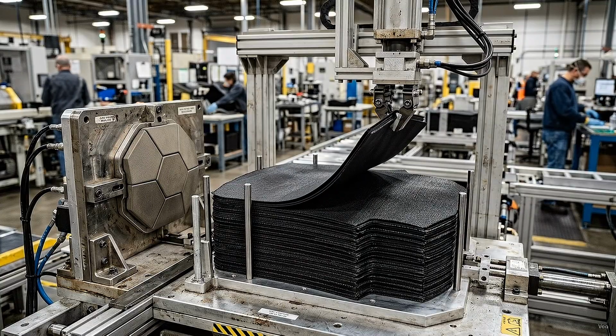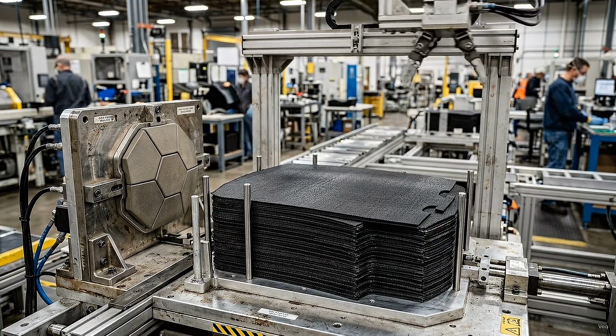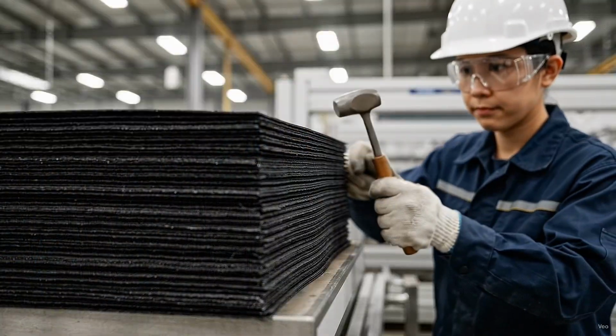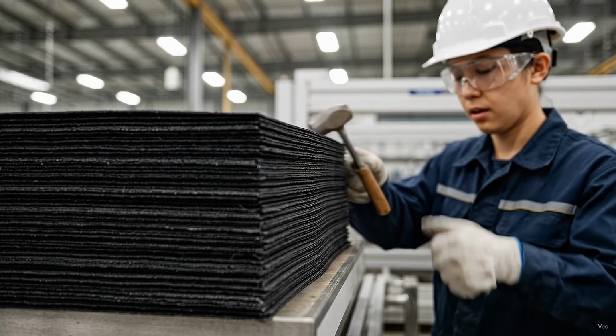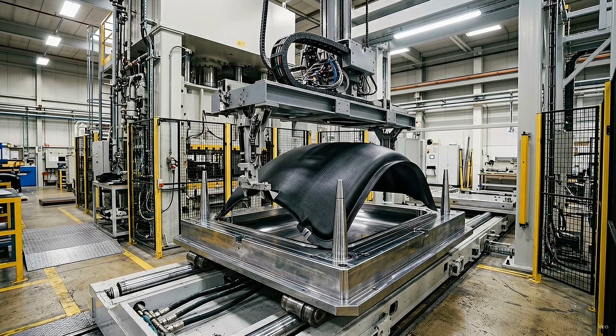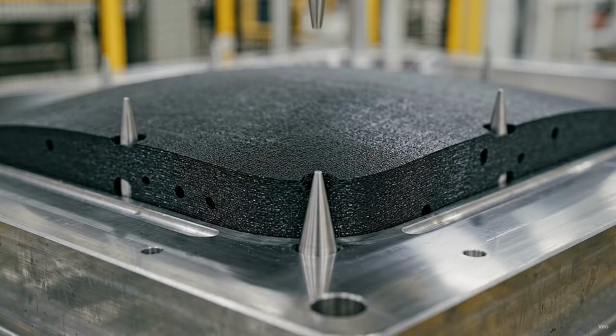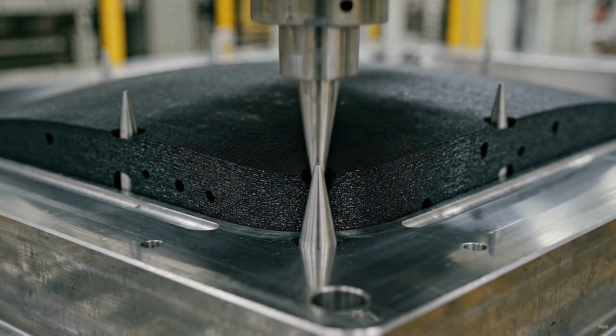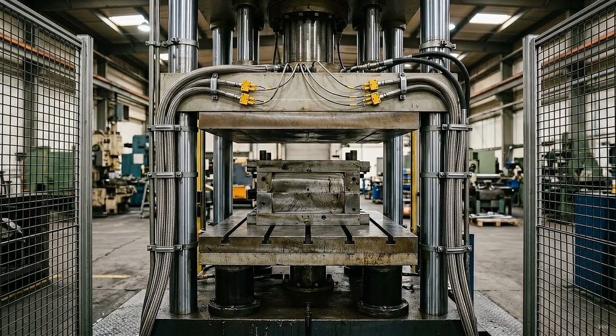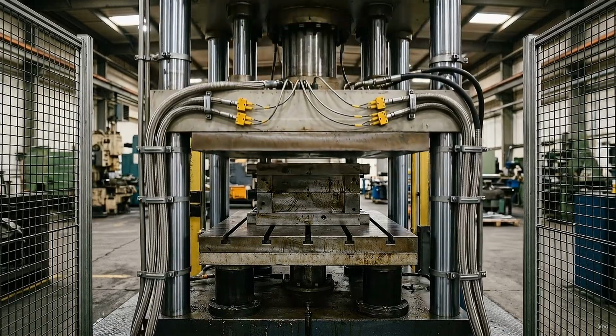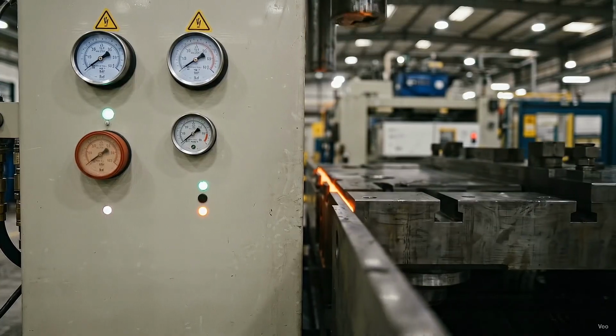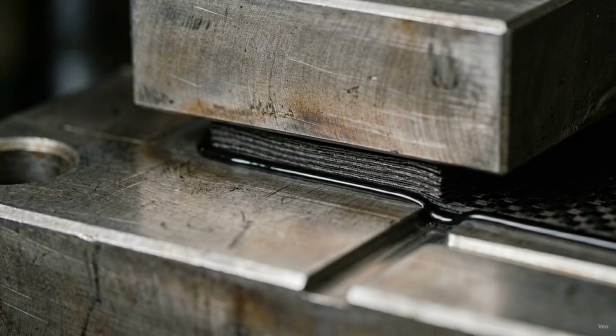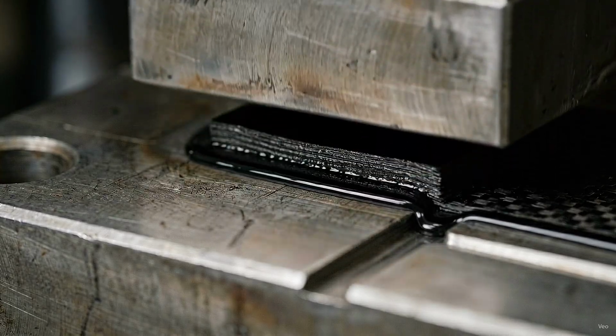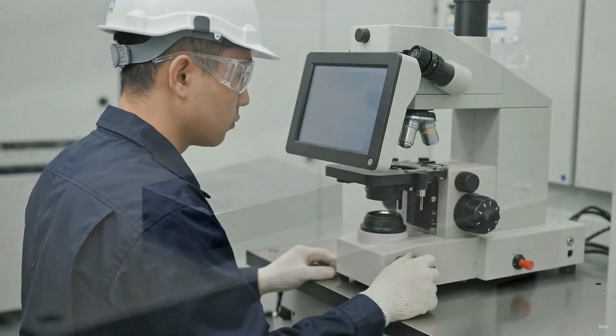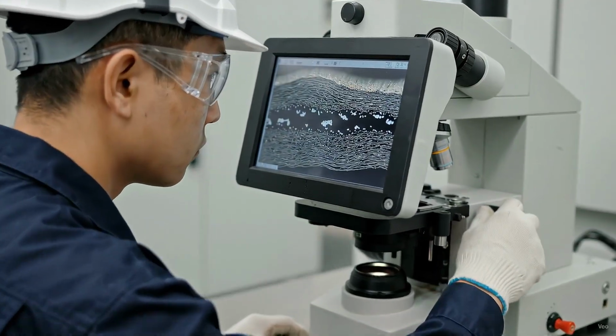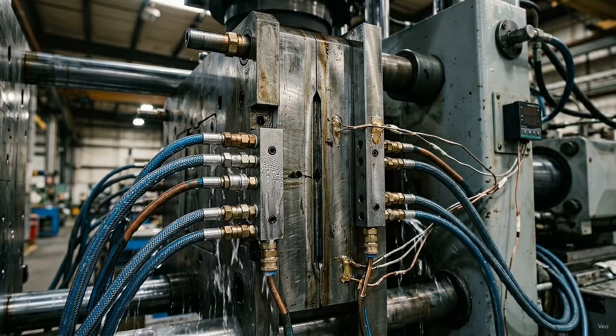Water jet cutters would trim the hardened panel into its required curved profile without overheating the composite edge. Robotic sanding would smooth the perimeter, and exposed edges would be sealed against moisture, abrasion, and accidental separation. The plate could then enter a reinforced textile carrier, but it would not yet be cleared for use. Laser scanners would compare curvature, thickness, and dimensions with the approved model. Scales would verify mass, since an unexplained change may indicate a missing layer, excessive resin, or contamination. Any unit outside the permitted range would be isolated.